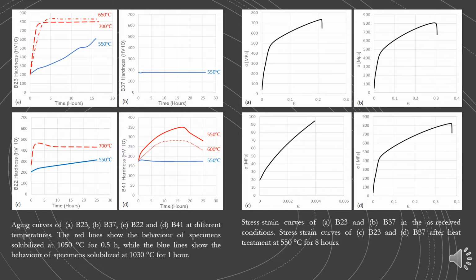On the right, the stress strain curve of B23 and B37 is shown before and after aging at 550 degrees Celsius for 8 hours. It is seen that B23 shows a very brittle behavior after 8 hours of aging and breaks in the elastic region. Again, this is due to the higher quantity of aluminium in B23.